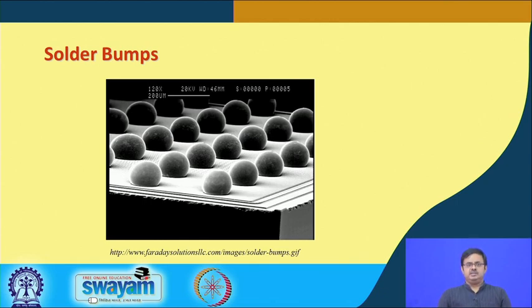This is a real picture, a scanning electron microscope or SEM image, and here you see the die with an array of these solder balls deposited or bumped on the active side or the front side. And now, this is ready to be flipped over and attached to the substrate. Okay. So, that is what we were discussing today, and that wraps up the first part of our flip chip bonding process.